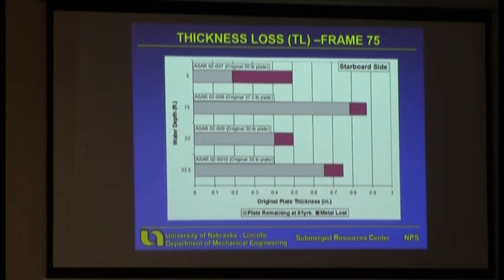So on the right side at 15 feet, the hull thickness is about 7/8 of an inch. And as we get to lower depths, 22 feet, the maximum thickness is 5/10 and subsequently 3/4 of an inch. But you can see the amount of metal lost as of 2002 is quite minimal. And that's been an important thing. So that's been important to us in realizing what's really happening on the ship, because this concretion is really just acting as a barrier.